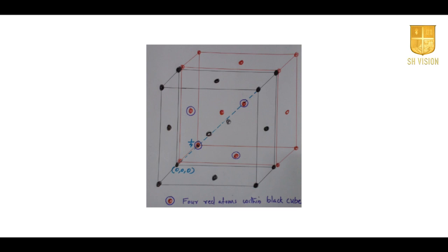So in the case of the diamond cubic crystal structure, there are 2 sets of lattice positions. These 2 sets of lattice positions, associated with 2 different face centered cubic Bravais lattices, are chemically identical but not equivalent. That is what we have seen. Chemically identical means all these lattice positions are attached with the same atom. In diamond, all are carbon atoms.